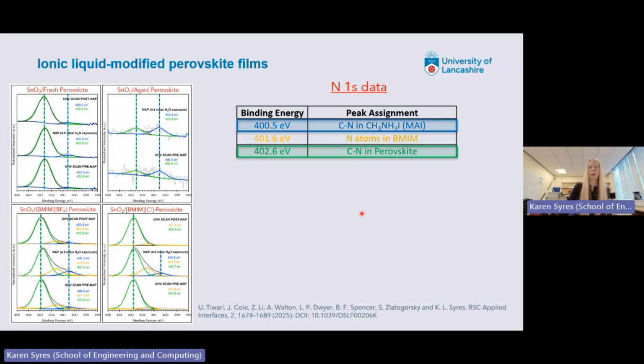The blue peak is the degradation peak that we don't want, and we can see that there's very little of that with the ionic liquid. The orange peak is actually inherent to the ionic liquid itself. So that's fine. That's just part of the ionic liquid.